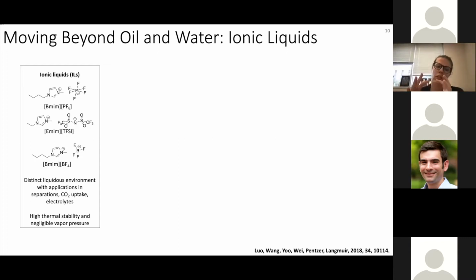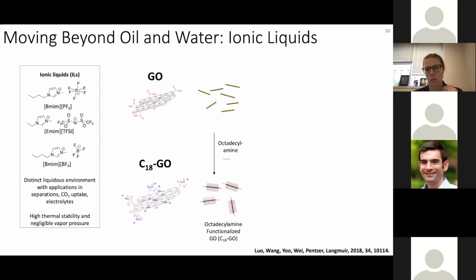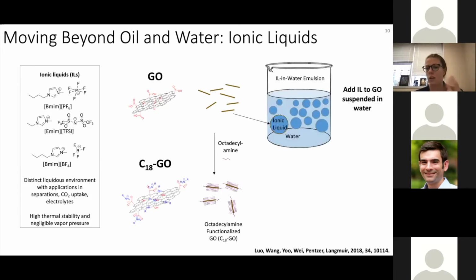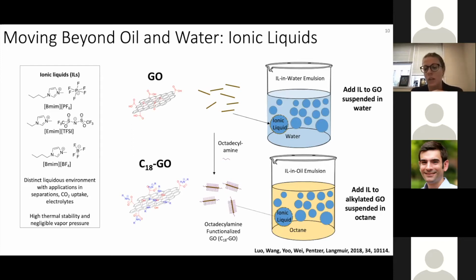And so we envisioned if we could stabilize either droplets or capsules of these, we'd be able to use them in applications that the bulk ionic liquids cannot be used for. So using the idea of if we have GO nanosheets dispersible in water, we could add an ionic liquid and stabilize ionic liquid droplets in water. And then alternatively, if we had the alkylated nanosheets, we could stabilize droplets of ionic liquid in octane. And so some ionic liquids are hygroscopic, and so you get a partition coefficient in slight miscibility. So the ionic liquid contains water and the water contains some ionic liquid. And so being able to use these non-aqueous emulsions gives us access to different